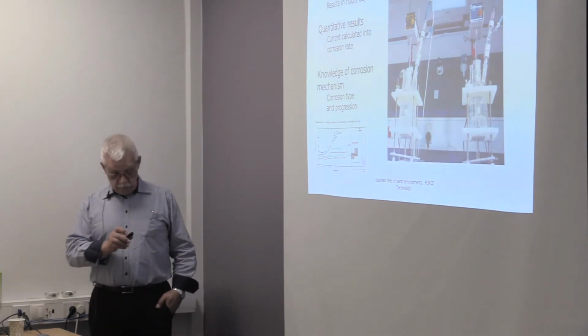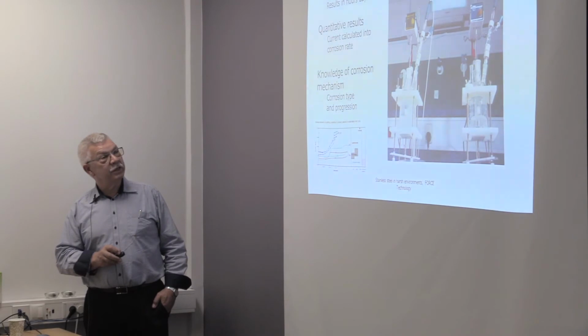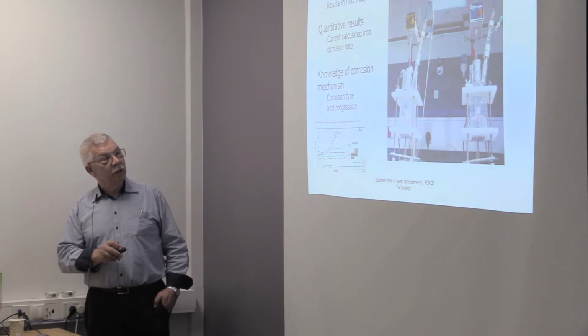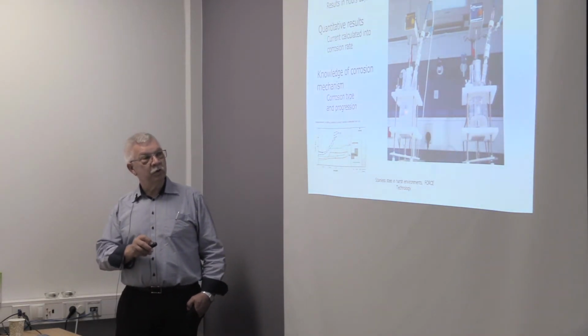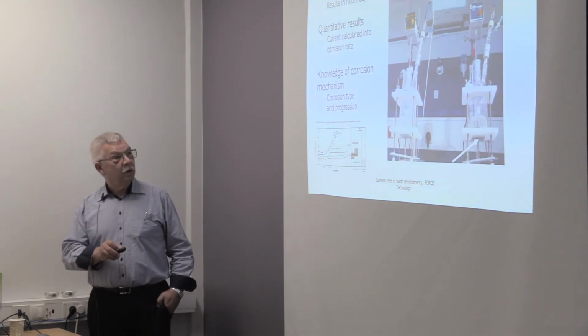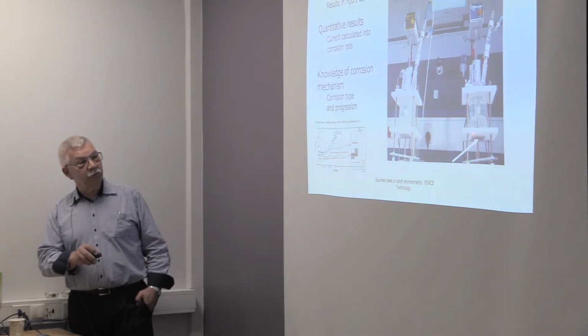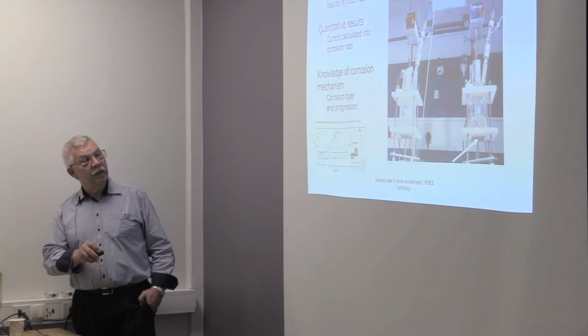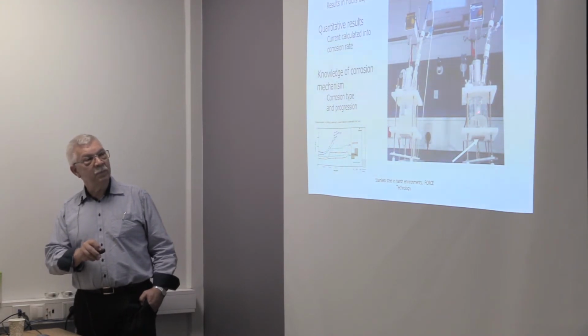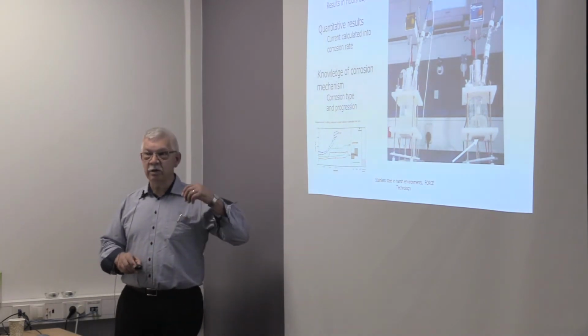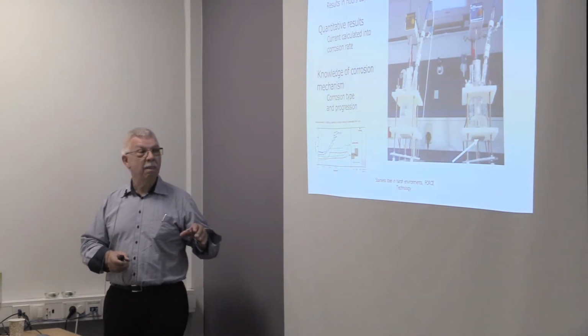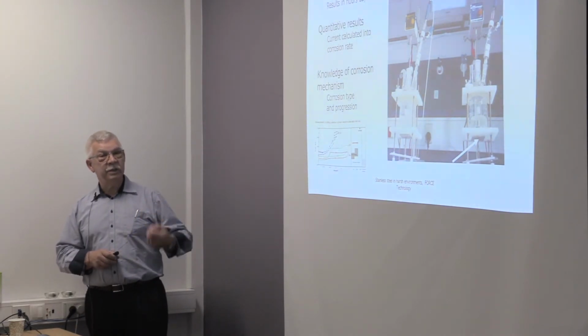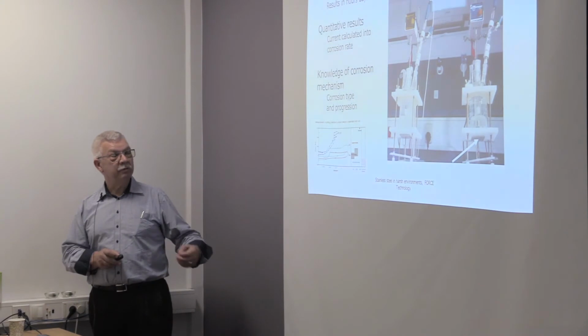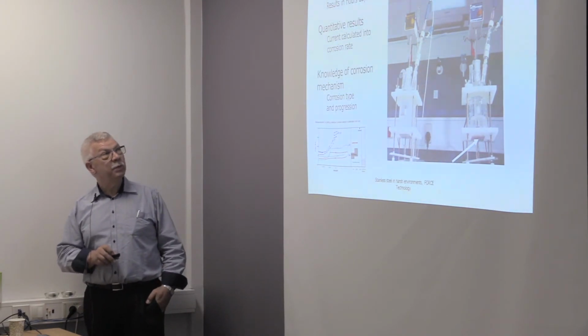This is some laboratory equipment for the electrochemical testing, where we have the solution in a chamber here. We have cooling water around to control the temperature, and the sample that we are testing is placed here and here, and there's of course an opening to the solution on top of it, and we can apply a potential, and we can measure when the current increases in this system. And when the current increases, we have a pitting which has been activated, and we have the temperature or the potential, whatever we measure.